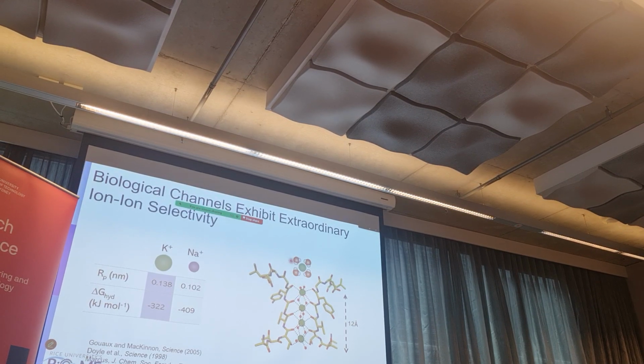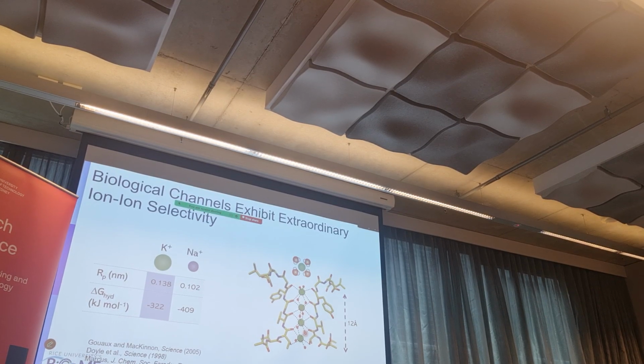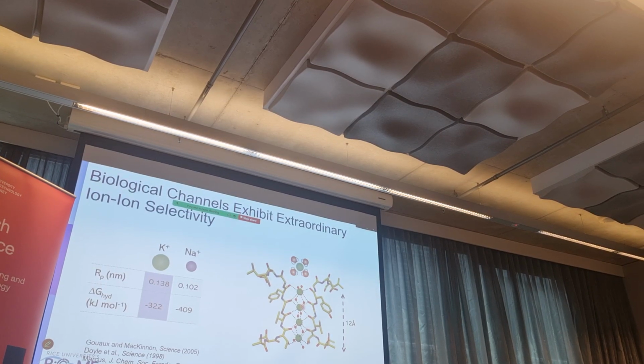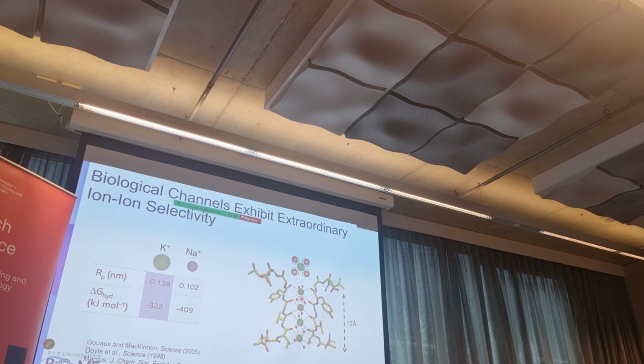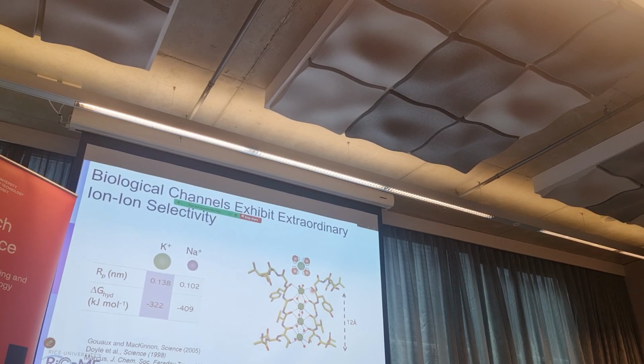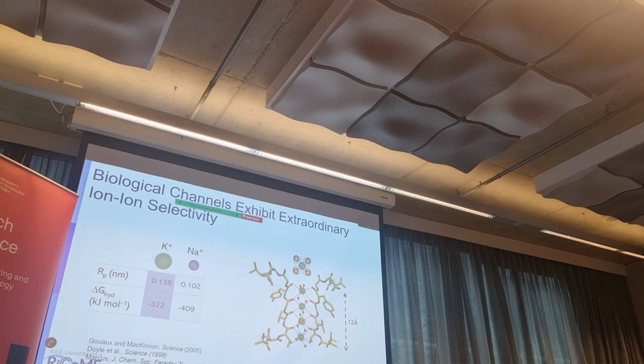And once we have this potassium, it can move by diffusion, by the chemical potential, and there are some other mechanisms like the knock-on effect, where if you have one potassium here and one potassium here, because they're positively charged, they push each other, and we get very, very nice selectivity. Again, the key here is the size, the complete dehydration, and the chemistry.